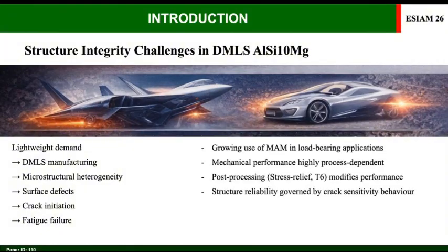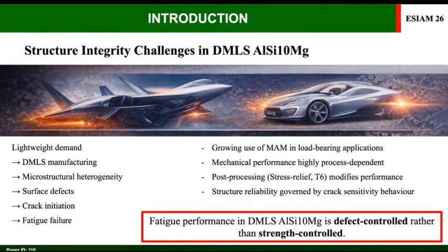To enhance the mechanical properties, post-treatments are frequently applied. These treatments modify the silicon morphology and stabilize the grain structure, improving hardness and ductility. However, from a structural integrity perspective, strength improvement alone does not guarantee reliability. Fatigue performance in AlSi10Mg is primarily governed by defect-induced crack initiation and propagation mechanisms. Therefore, the critical issue is not simply how strong the material is, but how it behaves when cracks initiate under cyclic loading.